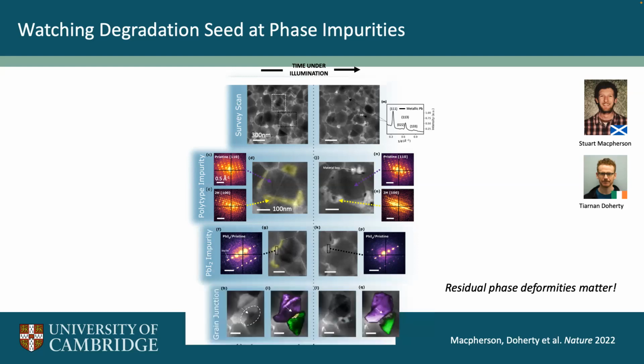And I'll give one more example where we see this interface here. We see these problematic phase impurities, and afterwards we see that that's degraded. But actually here we're starting to see that the perovskite is also starting to be eaten away as well. So what this is telling us is that these really tiny trap clusters are really problematic for degradation as well, and for the stability of these cells. That's something we really have to remove, both for performance but also for reliability of these materials.